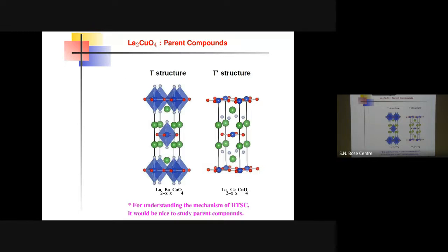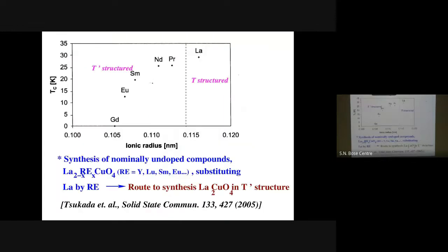So copper here is in an octahedral environment surrounded by 6 oxygen. Here it's in a square planar arrangement surrounded by 4 oxygen. And that actually made a big change. This is an experiment which was reported in 2005. What they did is, as a function of ionic radius of this lanthanide series, if the ionic radius is big, as for lanthanum, it will be a T structure, but as the ionic radius becomes smaller, just going beyond lanthanum, they are all in T prime structure.